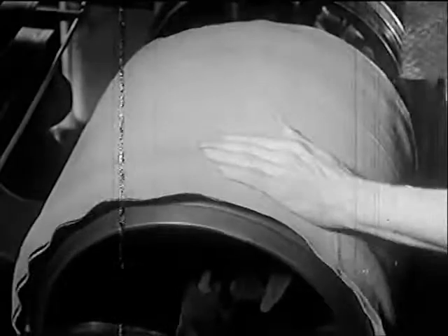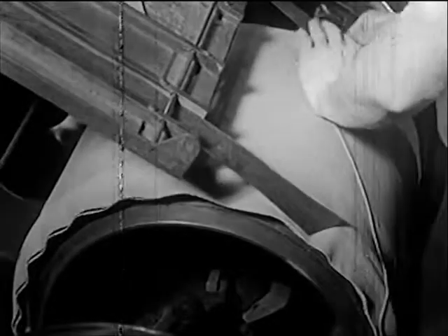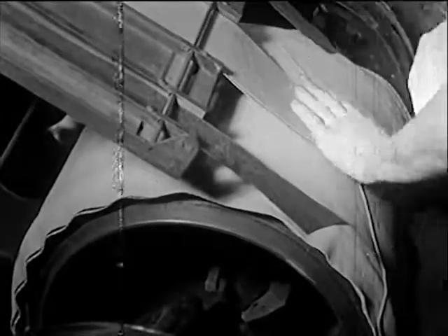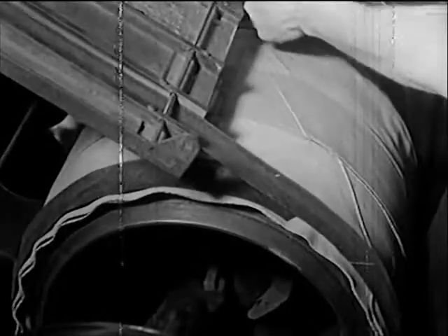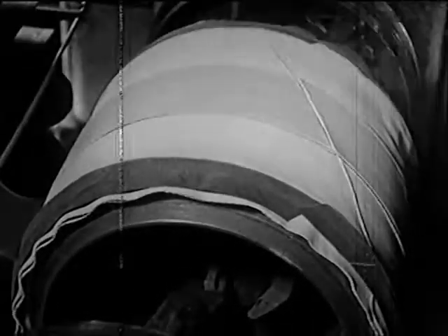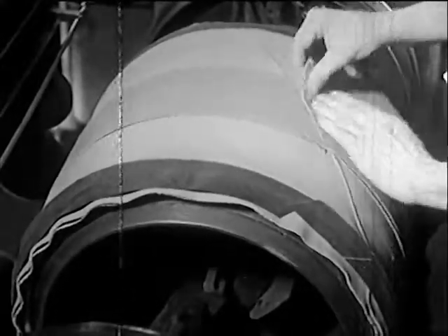One of the most common causes of premature tire failures and blowouts is the separation of the carcass and the tread. In order to eliminate this hazard, Brunswick has developed a double shock absorber unit. It consists of two extra layers of cord material treated and coated with a special cushion compound, which not only ensures positive adhesion of carcass and tread, but also protects the body of the tire from high-speed road shocks by absorbing and distributing them over a wide area of carcass. The double shock absorber is an exclusive Brunswick feature found only in Brunswick Super Service tires.